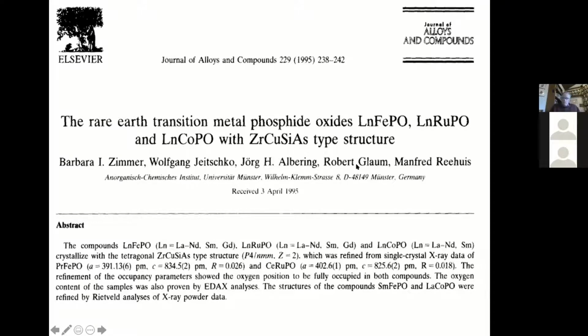And Barbara Zimmer apparently did her PhD thesis on this. And one of the interesting things about this work, an aside remark, is that she knew in her work that the lanthanum iron phosphorus oxide was in fact a roughly 5 Kelvin superconductor. And this is not even mentioned in the paper that reports the discovery of this compound, which to me, it was thought to be uninteresting that that was so. And yet here's Hosono later on, who did this work with fluorine doping that in fact generated TCs in this class of materials that got up over 50 Kelvin.